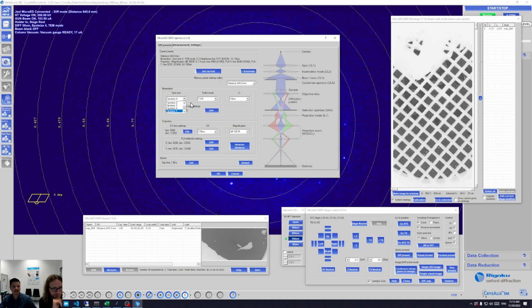Then you have the projection box below, which allows you to, for example, set the size of the region that you're diffracting from. And also, and this is most interesting, is this box up here, which is where you would select the detector distances. As I mentioned before, detector distances in this case doesn't mean that we physically move something, but that a zoom system, which is shown as projection zoom in this schematic on the right side, is set to different values. So now Kai has set this to, for example, 1015 millimeters instead of 645, and clicks on set current.